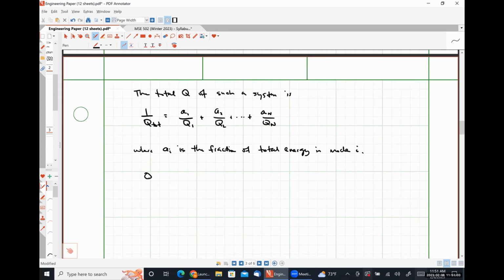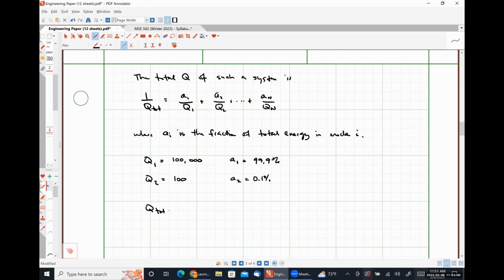So as a quick example here, let's say that we had a resonator with a quality factor of 100,000 and 99.9%, because that's what I did the math for, of the energy is associated with this first mode. And the quality factor of the second mode is 100, and only 0.1% of the resonator's total energy is associated with that second mode. What we'll find is that the total quality factor is 0.999 over 100,000 plus 0.001 over 100. Take the reciprocal of this thing, and our quality factor reduces down to 50,025 and some change, right?